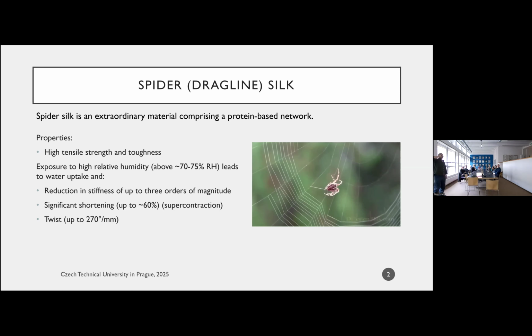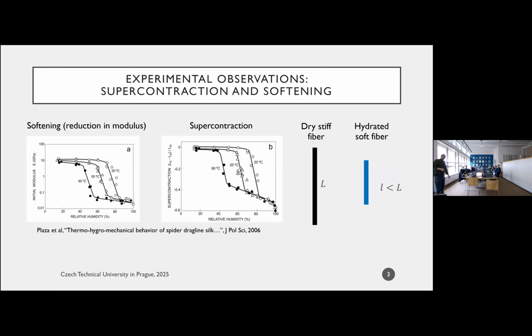Okay, anyways, so these are some experimental results. The supercontraction effect is well known. It's been investigated through and through. This is a paper that I very much like from 2006. What they've done in this work is they took a silk fiber and they measured its stiffness and its supercontraction strain as a function of relative humidity. Okay, and they've done that at 3 different temperatures. Let's focus on what happens at 20 degrees C.